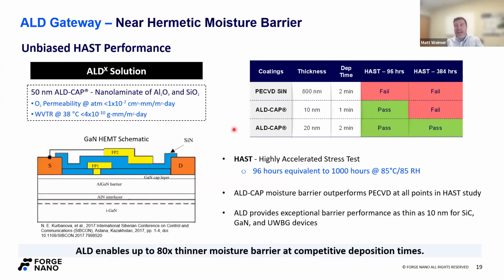So as I mentioned at the outset, a hermetic barrier is where ALD is the first thing people think about when they think about ALD. And so, I've put this GaN-HEMT schematic here for consistency. We call our platform the ALD to the X platform, and we have a product that we call the ALD cap. Typically, it's a nanolaminate. So remember, that's the 2 individual layers, repeated, of aluminum oxide and silicon oxide, though we can mix and match depending on the application and the need.